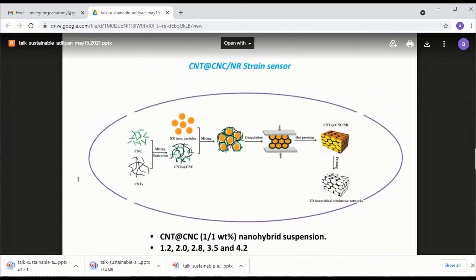So, in this protocol, what we have done is we combined carbon nanotube. We also did some hybrid work. We combined nanocellulose and carbon nanotube together. So look at this. This is nanocellulose, this is CNT. And then we mixed it with natural rubber latex. This is rubber latex. We mixed them together, went for a coagulation process, then hot pressing. And finally, we got CNT nanocellulose composite.